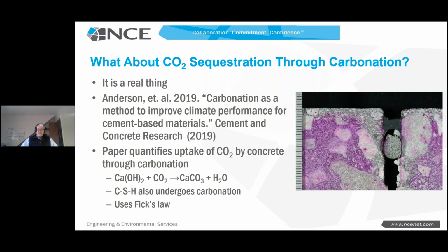And the picture on the right shows basically a concrete specimen that's been slabbed and stained with phenolphthalein, and you can see the carbonation front in this specimen. This is a pavement, that's a joint, and so you can see how we got some carbonation. Everything that's not pink has carbonated. And this is kind of typical for a pavement, what we're seeing here on the right.